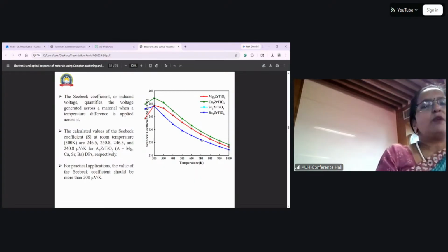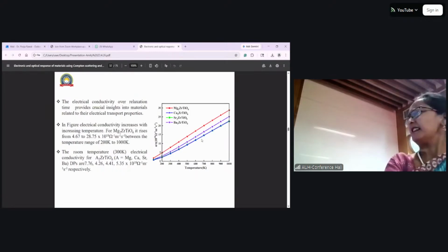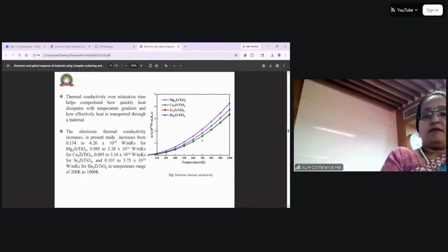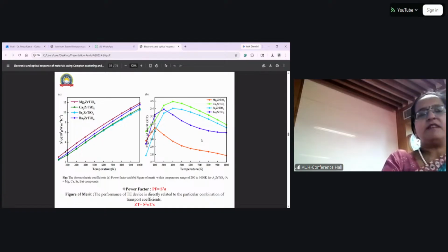So for all the studied compounds, it was in the acceptable region, and at room temperature it was greater than 200 microvolt per Kelvin. Then the electrical conductivity, I think something went wrong with the PPTs. So it was up to that particular value. Electrical conductivity shows whether the material will be suitable for conduction or not, and we found that all the materials that we have computed have good electrical conductivity at room temperature. Similarly, thermal conductivity for practical application should be as small as possible. We obtained the same result for this, and the same with the figure of merit, etc.